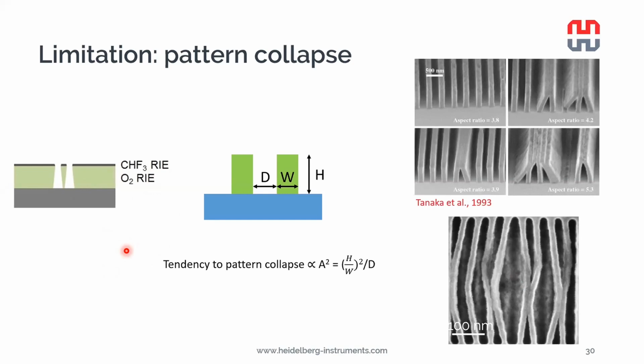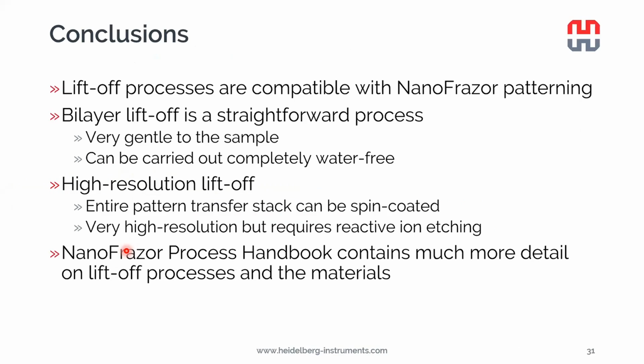Okay, in conclusion, I showed that the liftoff processes are compatible with the NanoFrazor patterning. So we have these two processes, the bilayer liftoff. It's a very straightforward, quick, easy to use process. It's also very gentle. It enables making contacts with minimum invasiveness to your sensitive material. And as a bonus, it can also be made completely water-free in a glove box environment.